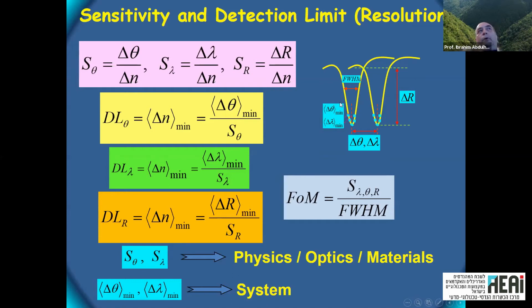If we have this curve very narrow, we need a high resolution spectrometer. Maybe we need much more precise angle measurement. So the beam has to be much cleaner, and we need very fine rotation stage and so on. So the system becomes more expensive. But it depends on your requirement. If you do not need this high resolution, like very low detection limit, then you can choose, for example, standard off-the-shelf spectrometer, and that's good enough.